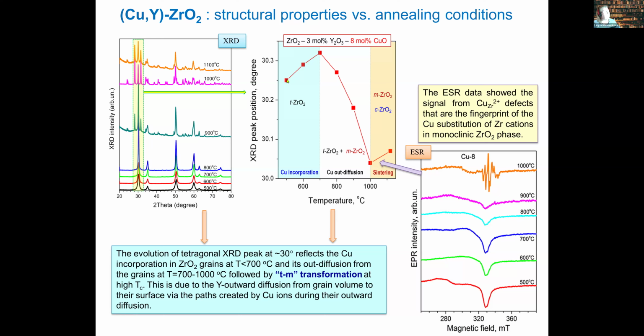You can see that at first we have a shift to higher angles, which says something about copper incorporation inside the zirconia grains. Then at high temperatures, after 700 degrees C, it goes in the opposite direction. This means that we have transformation of tetragonal, losing tetragonality, and formation of monoclinic zirconium oxide. And at the highest temperatures, we have a bit backward, and we detected both monoclinic zirconium oxide and cubic zirconium oxide.